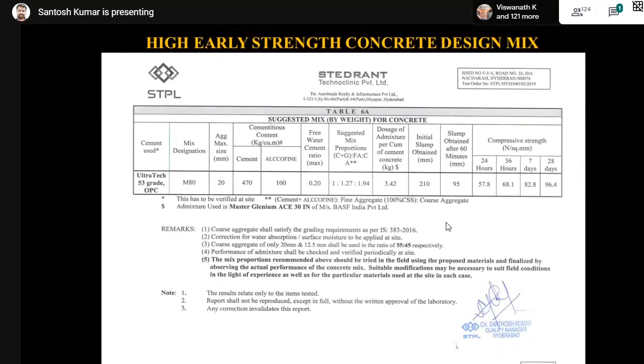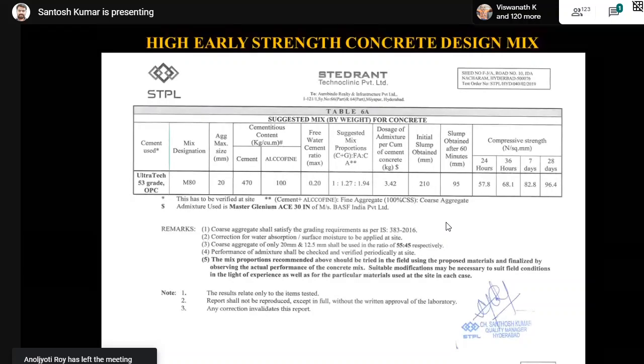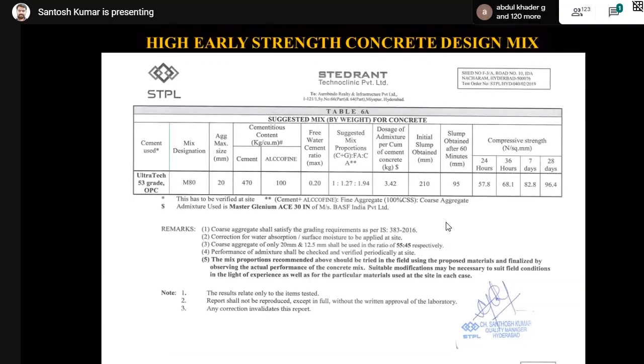The water cement ratio was only 0.20 for M80 grade of concrete. And imagine, the 24 hours compressive strength was 57.8 Newton per mm square. The requirement was only 50 MPa. We gave 57.8 MPa at the end of 24 hours. And at the end of 36 hours, it was 68.1. At 7 days, it was 82. And at 28 days, it was 96.4.